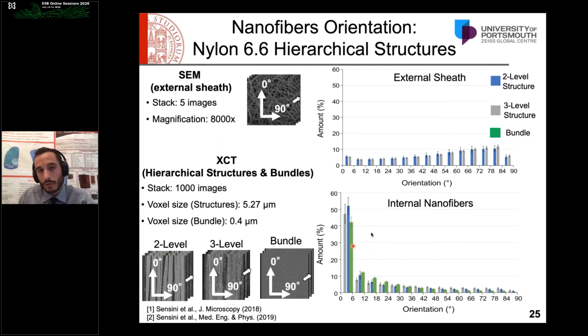You can see also in green the result for the single bundle nanofibers. And you can see that again, the majority of the nanofibers and bundles result actually aligned inside the structures, with a progressive circumferential scatter.